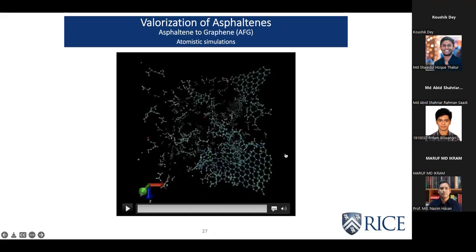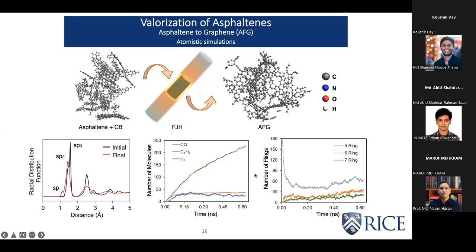From these molecular simulations, we got very interesting information about the flash Joule heating process. That is, carbon black not only provides the required conductivity, but it also acts as the nucleating agent. That means these ordered 5-, 6-, and 7-membered rings start growing around the carbon black. So that was interesting information that we got from the molecular simulations. We also got what other types of gases were being evolved, and the 5-, 6-, and 7-membered rings being formed during the process.